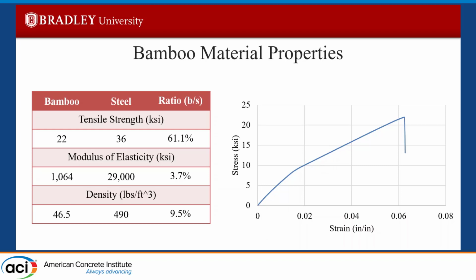And then we're comparing this to A36 steel in this case, which has around 36 KSI tensile strength, 29,000 KSI for modulus of elasticity, and 490 pounds per foot cubed, which is all pretty well known. And on the right-hand side of this table, we have the ratio of bamboo to steel. So for tensile strength, 61%, modulus of elasticity 3.7%, and density around 9.5%.